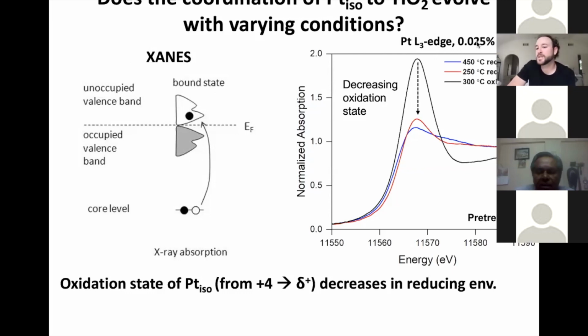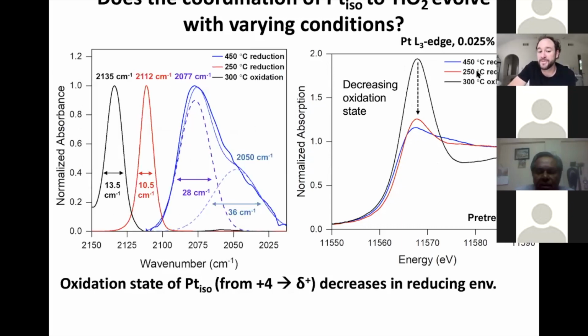And so what we could see is for our sample that we've been characterizing for the last few slides, the oxidation state of platinum changed as we put it under different environmental conditions. So these were all in situ. And through comparison with standards, we could say that when we pre-oxidize this sample, actually it looks like platinum's in a +4 oxidation state. When we mildly reduce it, as we have been doing at 250C, it looks like it drops to close to a +2 oxidation state, and then even further down to a delta+ oxidation state as we reduce this thing even more harshly. So clearly, the local coordination environment of platinum is evolving. I'm going to skip this just briefly.